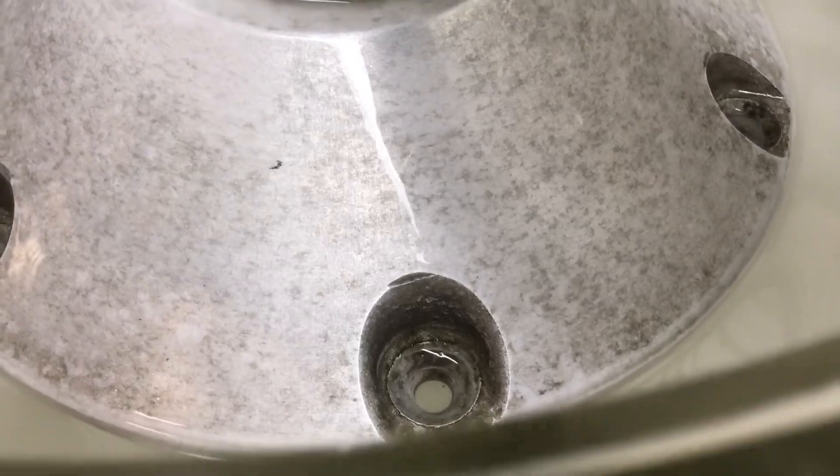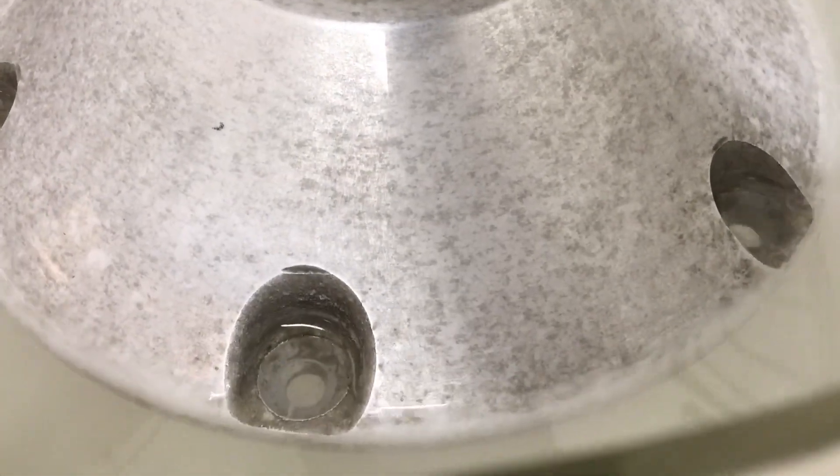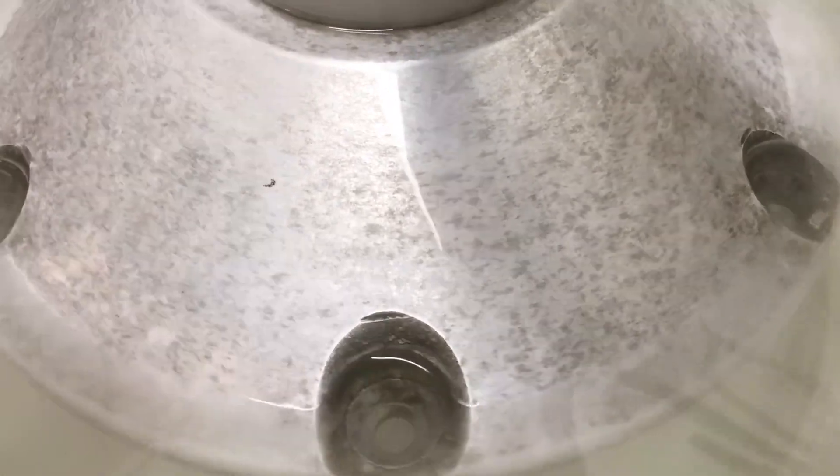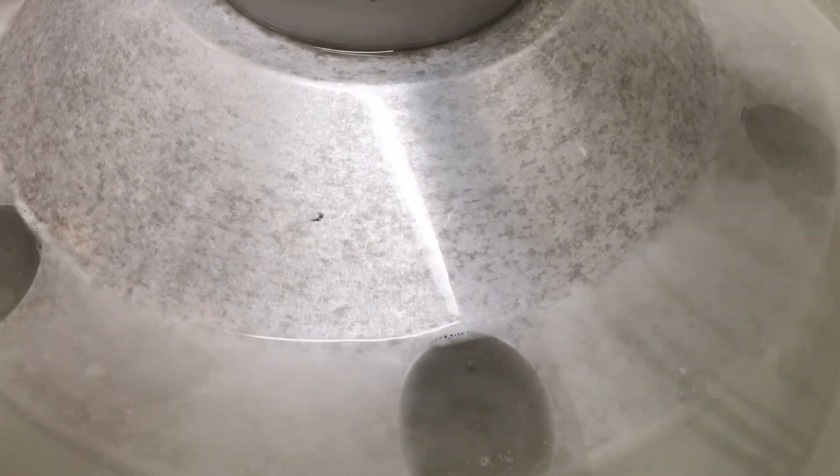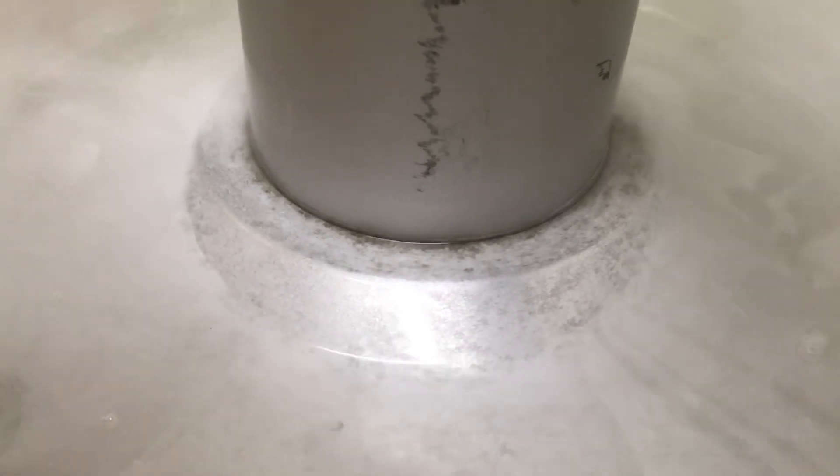If I bring it up, you can see that the more darker spots, that's where you had more aluminum oxide sitting, and the brightest spot is where the aluminum was more accessible. Not much is happening to the anodized aluminum because it takes much more time to penetrate through the oxidation layer that they put on electrochemically on the extruded tube. But you can already now see how the entire piece is becoming more shiny.